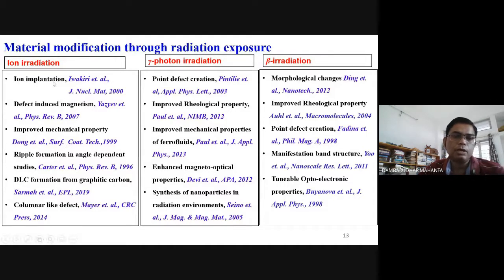Ion implantation means if you want to put some dopants into some layered materials to improve electronic properties. In the second case, Yazyev et al., defect induced magnetism. If you want magnetism in a substance without incorporating iron, cobalt, nickel, because of defects you can generate magnetism. So this is another report. Mechanical properties can also be improved because of radiation. You have ripple formation in angle dependent studies. One can form a number of ripples, and these ripples can act as diffraction grating for certain applications.